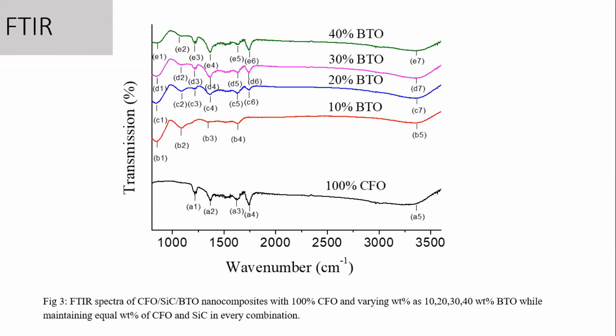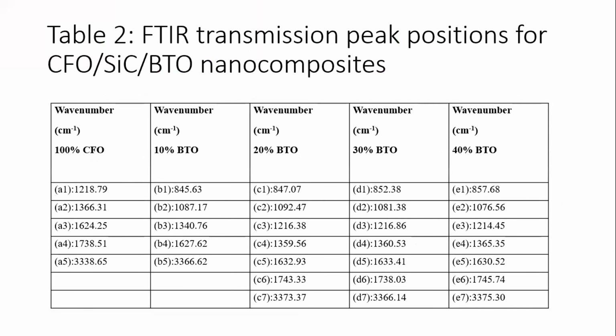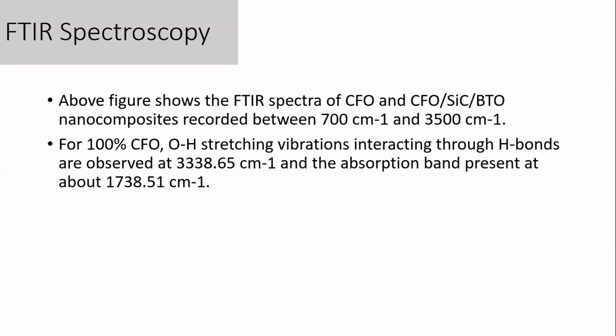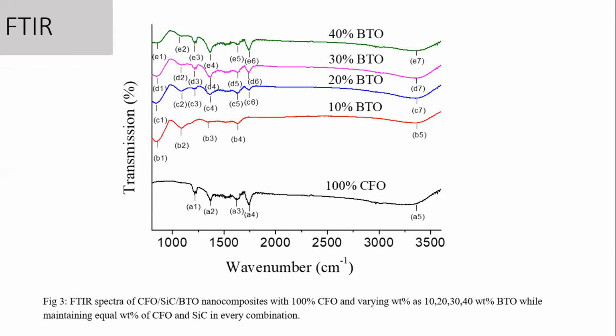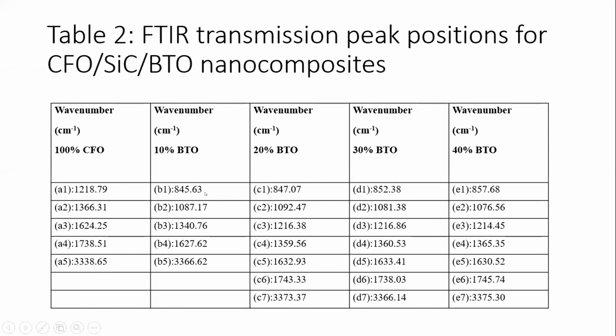This is the FTIR spectra of our nanocomposites. We have tried to identify all the peaks, and the peak positions have been showcased in this table. Again, we could figure that for 100% CFO, the peak here, we can also look at the exact wave number here from the table.